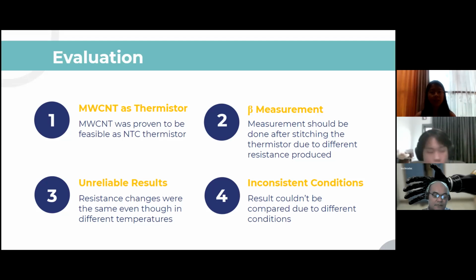As we could see before, the reference resistance is around 60 kilo ohms before stitching, but after stitching the reference resistance is around 40 kilo ohms. So they made a mistake there. And it is crucial because the beta value and the reference resistance will be used for the Arduino coding, and it will then affect the results. And then the unreliable results here, the resistance changes were the same, like I have shown also before, that